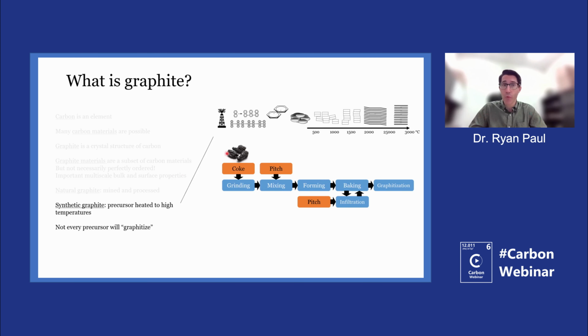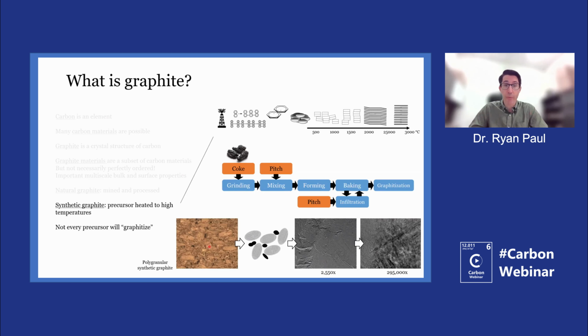And today there's a big use for sort of a polygranular composite of mixing together different ingredients and heat treating those. So, for example, a manufactured graphite material, as is schematically shown here, would involve mixing together these different carbonaceous particles that are sized with a pitch as a binder or a glue that holds it together, mixed and formed. There's various ways to form, like extrusion and molding. And these are heat treated all the way through graphitization temperatures, depending on what you're trying to get in the end, to create this sort of synthetic graphite composite-like material, which retains its very polygranular shape.